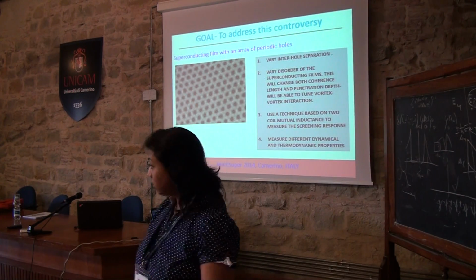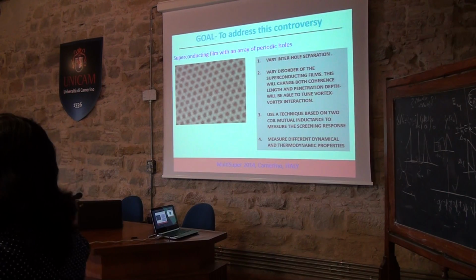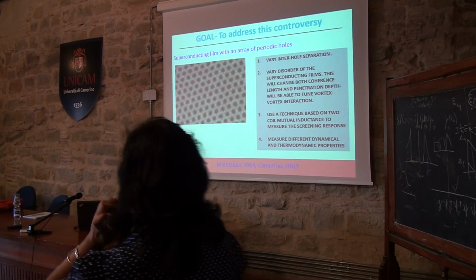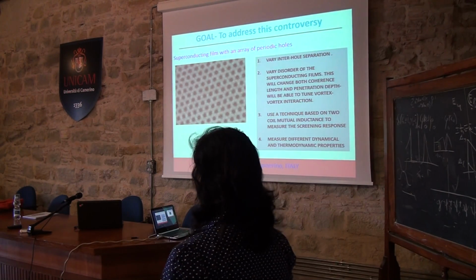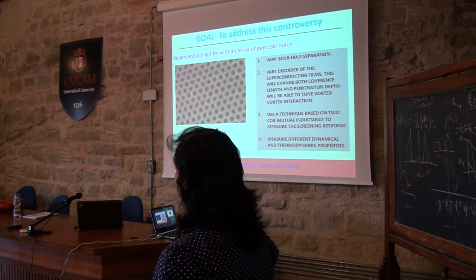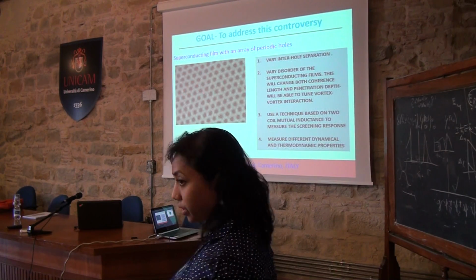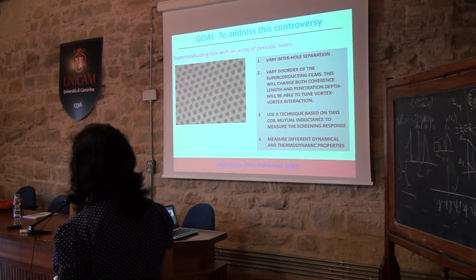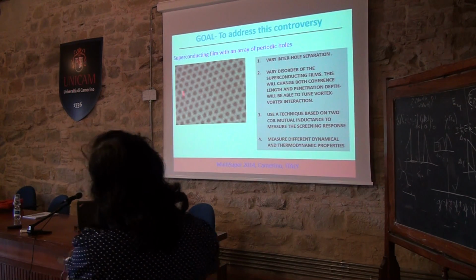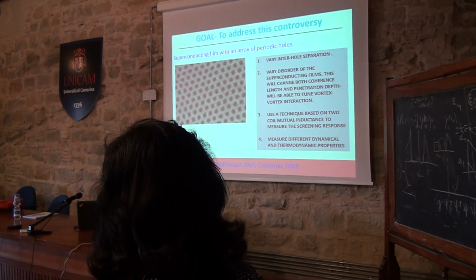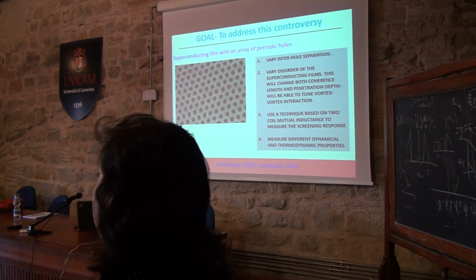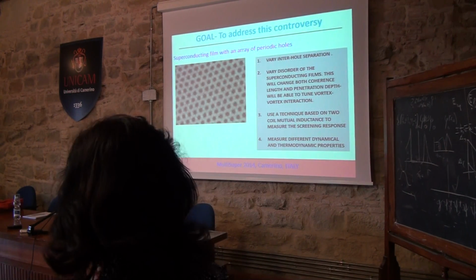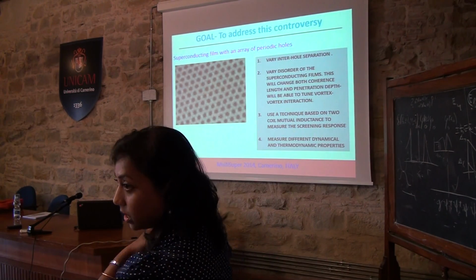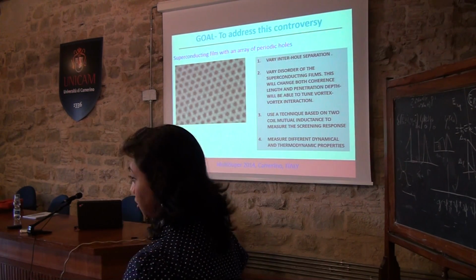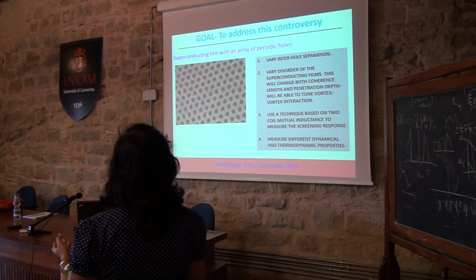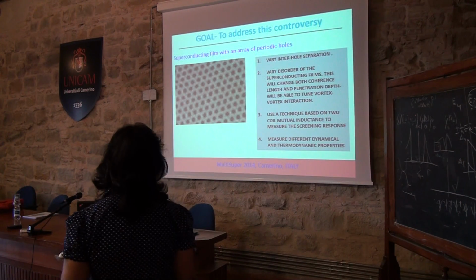So we wanted to address this controversy, and to address this controversy we had different tools. First, we wanted to see what is the effect of matching effect on the interpore separation. So if you change the interpore separation, how should the matching effects change? We also wanted to vary the disorder of the superconducting films, because the disorder would change the superconducting properties like the coherence length and the penetration depth, which would in turn be able to tune the intervortex interaction.